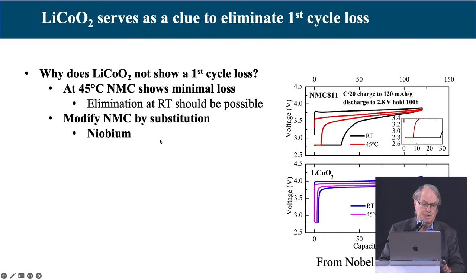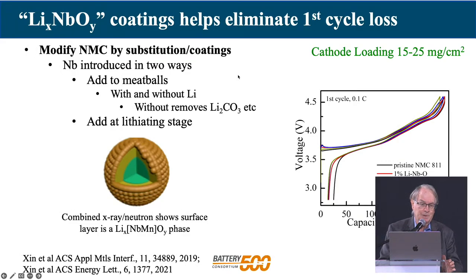So we particularly chose niobium. And what we did is substitute niobium in the lattice and on the surface. And you control which one happens by just changing the temperature, say from 500 degrees it's surface coating, at 700 degrees it's fully inside. But even with the surface coating as shown here, it's more complicated because as some of the niobium goes into the lattice, some of the manganese comes out. So it turns out the surface coating is a mixture of lithium, niobium, manganese, and oxygen. But you can see even with just 1% niobium in here, we've eliminated half that first cycle loss. So modifying the material using niobium does work.